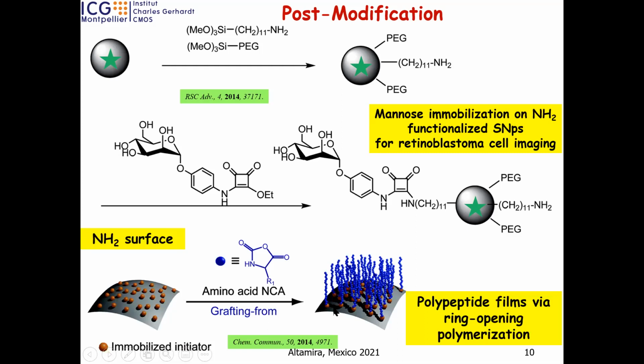Just next slide. Here you have another example, if you want to make a branched polypeptide thin film on top of any type of substrate. You have to activate it with amino group. Then a reaction with activated amino acid by ring opening. You open and you generate an amino group here, and the amino group reacts with another precursor, and so on, and you can grow. Here you have a linear chain on the surface.